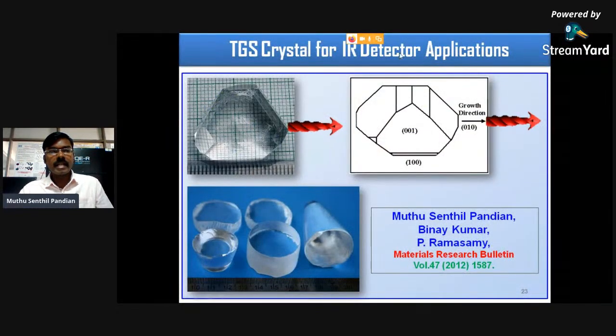So this is the triglycine sulfate single crystal, TGS crystal, for ferroelectric application, pyroelectric application. As I told you, we cannot use this conventionally grown crystal for practical device application. Only this polar b axis, this single portion, is useful for pyroelectric application. So the other portions are wasted in the conventional method. We have to dissolve it again in the beaker and grow the crystals by the SR method. This is the conventional method grown TGS crystal. This is the polar b directed TGS single crystal for ferroelectric pyroelectric application.